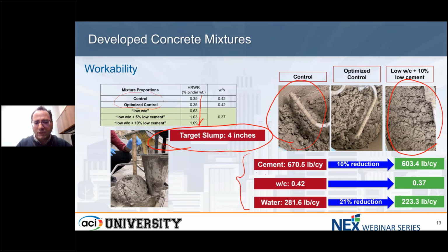So cement for control one is 670.5 pounds per cubic yard. We reduce that by 10% for this sustainable mix to 603 pounds per cubic yard. The water cement ratio, as I mentioned, we reduced by 12%. And by doing so, the water content reduced from 281 pounds to 223 pounds. That's almost a 21% reduction in the water content. So that's how we basically screened the different mixes we tested to get to this point, to get to our goal, which I discussed in the previous slide.